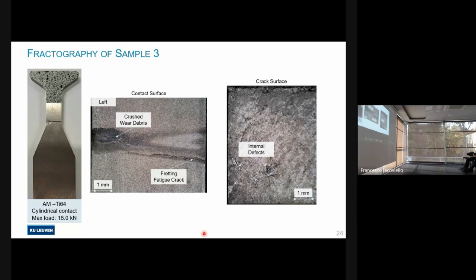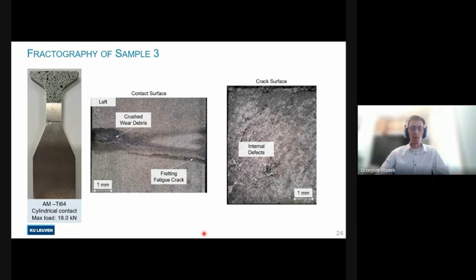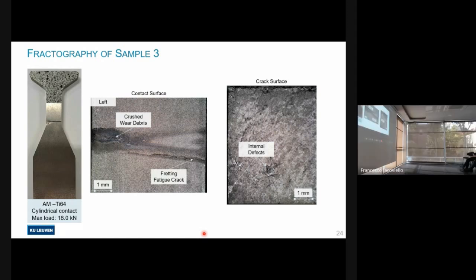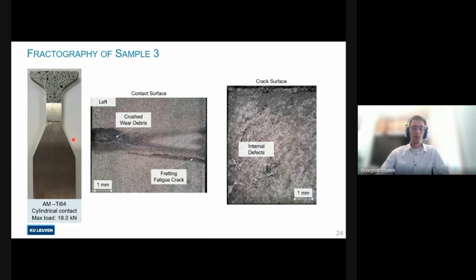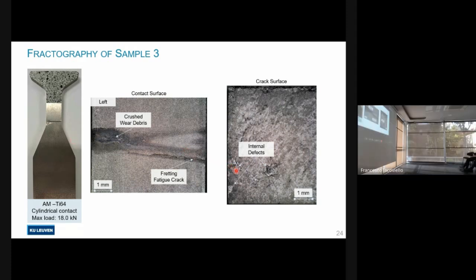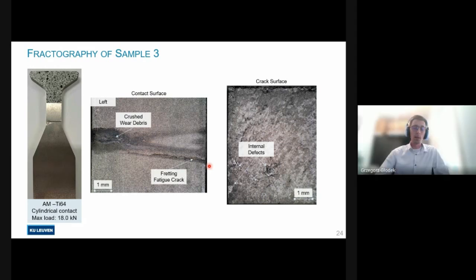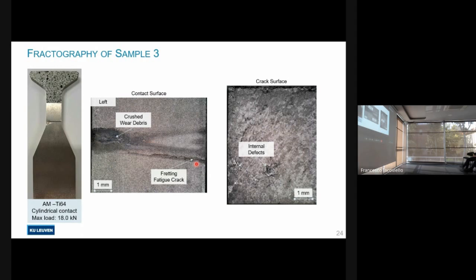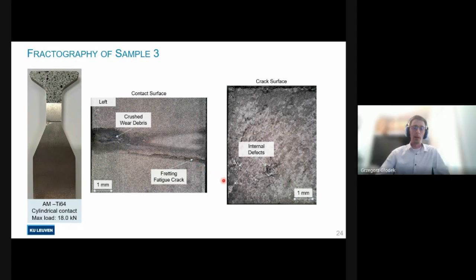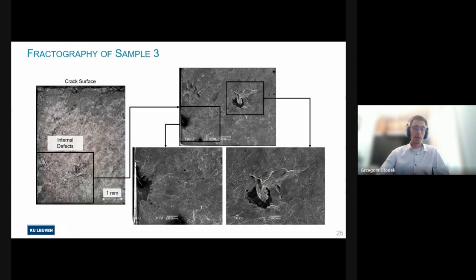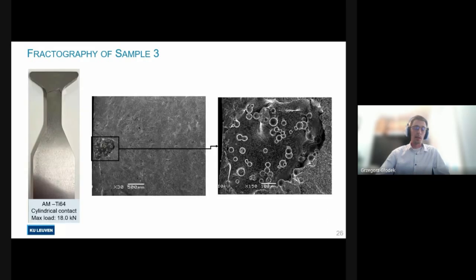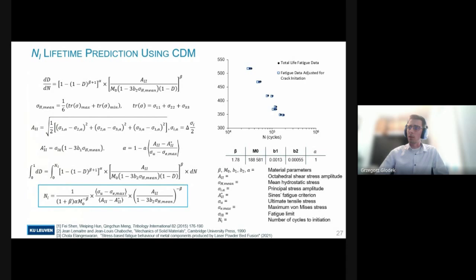So this is another example of a failure out of contact that occurred due to internal defects. But in this case, the fretting fatigue crack managed to initiate, but didn't have time to propagate, and the failure occurred here in the neck area. And a similar story with the last sample that failed outside the contact area.